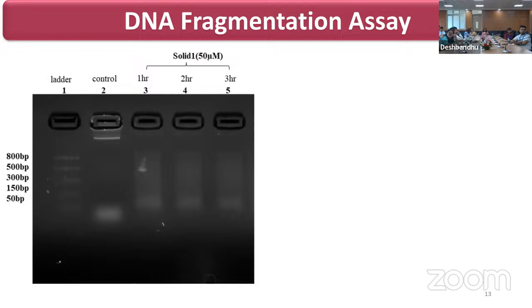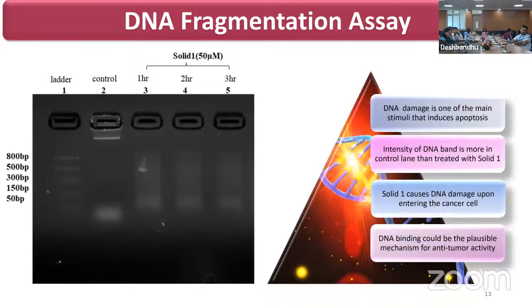So we went on to check the DNA fragmentation assay, and to our surprise, we found that the control lane, which is the untreated one, where the synthesized form is not added, is showing the highest intensity band. And as we treat the plasmid DNA with the solid, the intensity gradually goes on decreasing after 1, 2, and 3 hours, which shows that our synthesized solid is actually causing DNA damage. As DNA damage is one of the main stimuli that induces apoptosis, we can say that DNA binding could be the plausible mechanism for the anti-cancer activity.